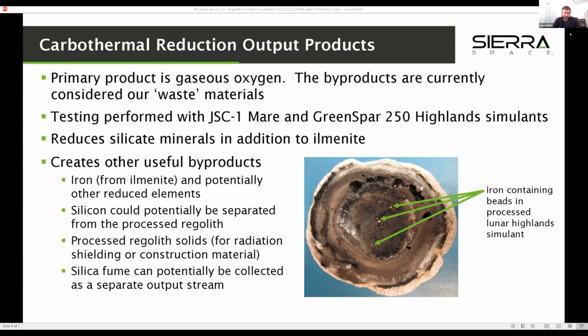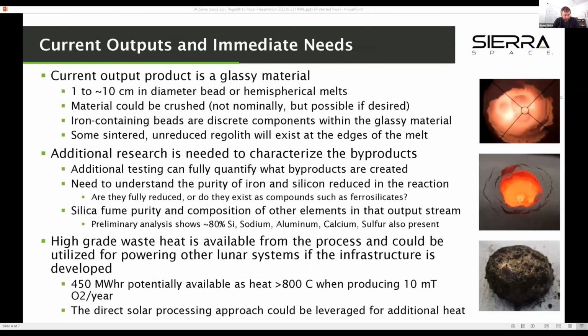which is created as a byproduct in the reaction, and that's extracted out as a gaseous process stream that's condensed. So that might be a really attractive way for people to get access to silicon out of this process without having to do something like grinding up and post-processing the melts where the other reduced silicon is. And then just to note, you can see there's some little iron beads there. That's actually the Highland simulant, so there is some iron present in it. But the iron is immiscible in the greater overall melt, so it would be a little easier, I think, to separate out in post-processing. Next slide.